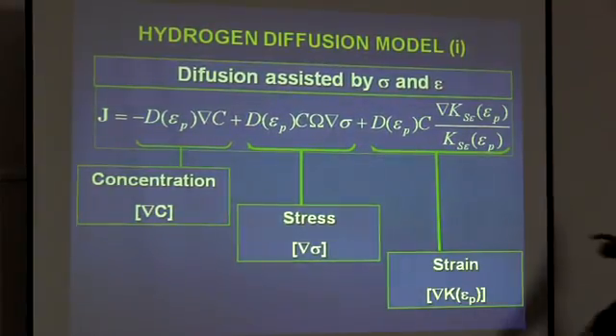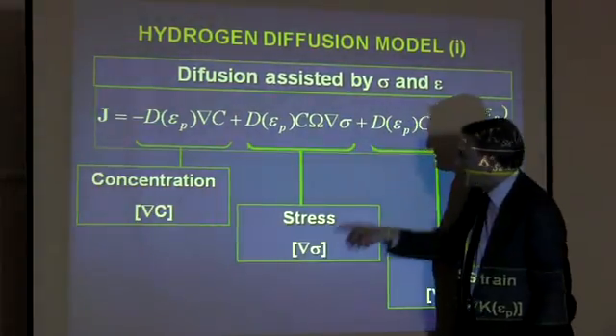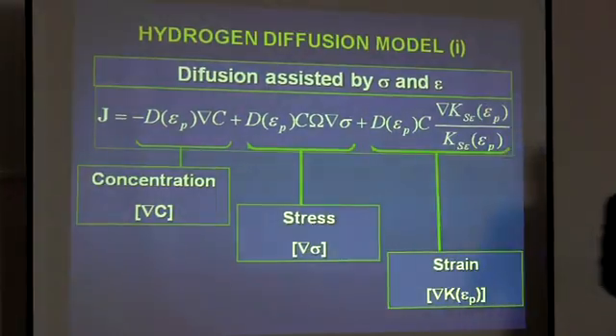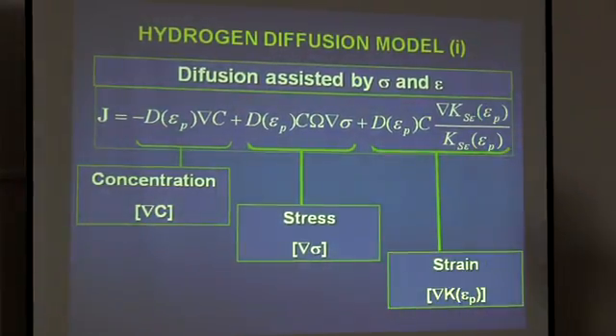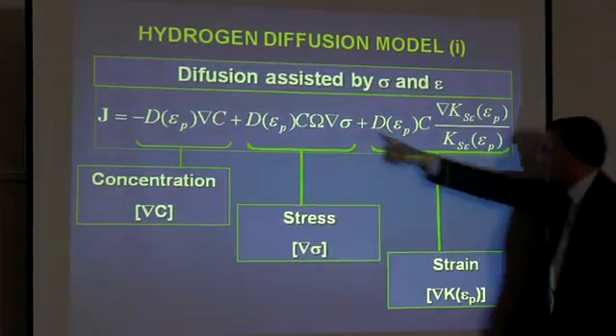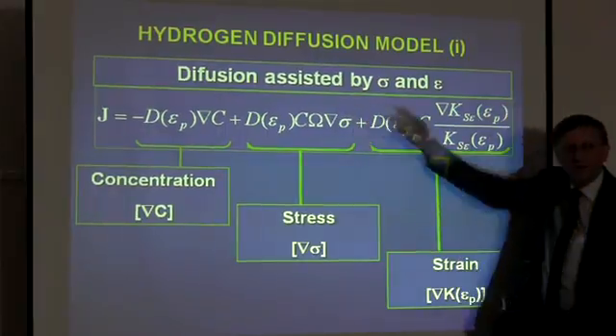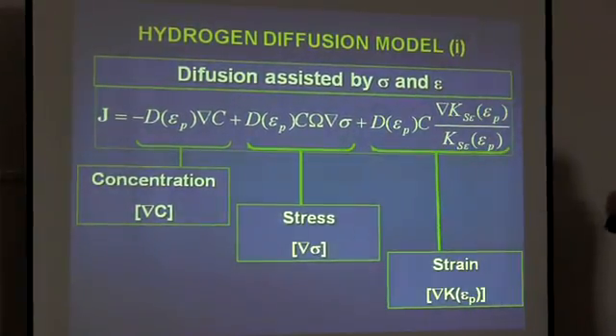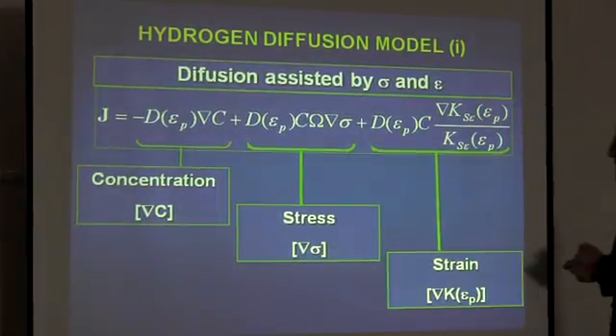In addition, the stress-assisted term, depending on the positive gradient of hydrostatic stress: hydrogen diffuses towards the points of maximum hydrostatic strain, which is in a one-to-one relation with hydrostatic stress. It's a mathematical question, it could be hydrostatic strain in a place in the mesh.